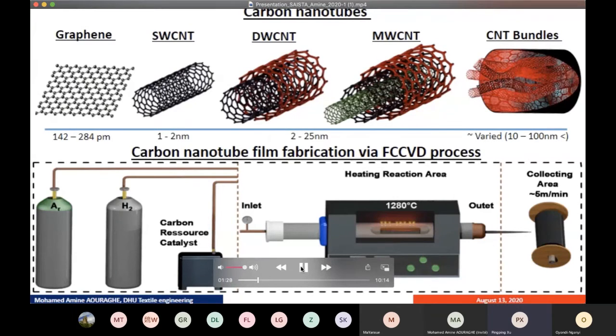Depending on the process used, we can fabricate highly aligned CNTs such as arc discharge, laser ablation, but those methods are time-consuming and expensive. In our work, we use the floating catalyst chemical vapor deposition method, which is the most effective process to produce and assemble CNT into a macro scale. The produced CNT are like film or buckypaper and could be turned into yarn or rope, or directly used as a film according to the application needed.